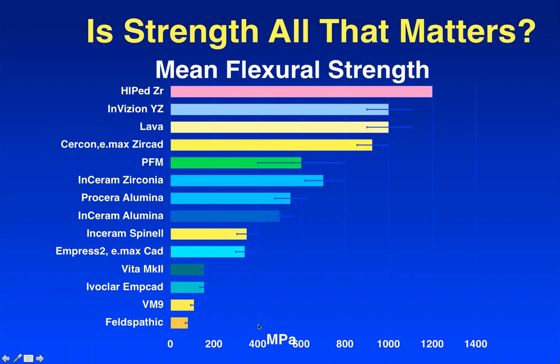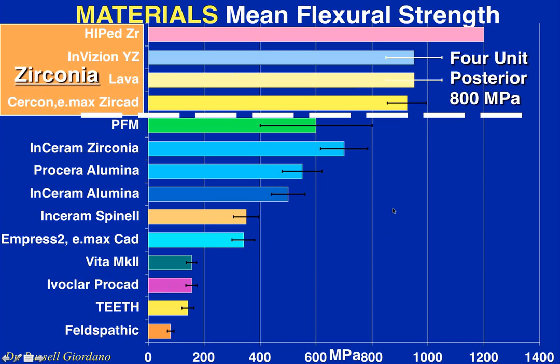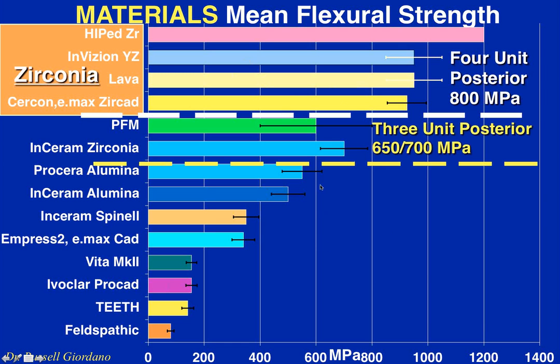And it's not really very meaningful just looking at megapascals. What you need to do is start combining the megapascals with clinical trial data. And for ceramics, the higher stress you're going to put on it, the stronger they generally have to be if they're a pure ceramic material. However, processing is very important, and how you treat the material when you are placing it in the mouth is also very important. So we have zirconia up here. If you look at some clinical studies, it really has to be about 800 megapascals or so for the strength to be sufficient for a stiff ceramic.